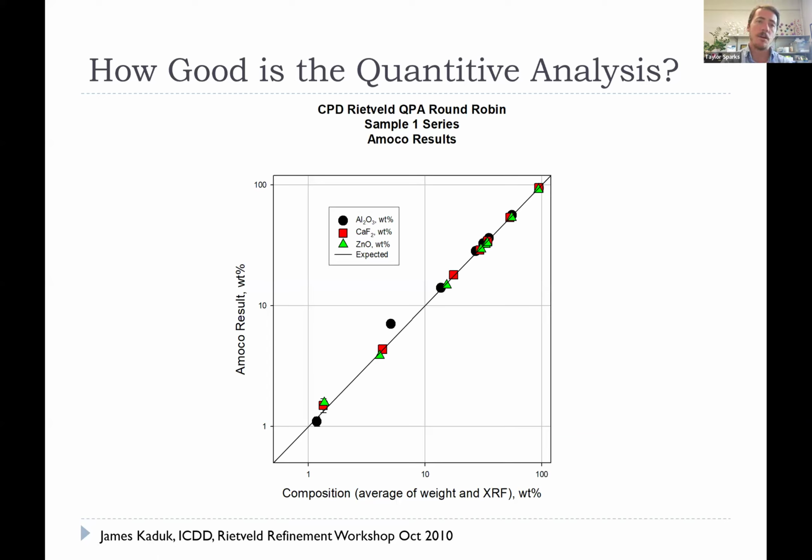If you're using lab x-rays, like if you're working in industry or at a national lab, and you're doing just a regular benchtop or a standard X-ray diffraction system, you can expect to get weight fractions accurate down to a few weight percent, like maybe 5 weight percent. If you're reporting less than that, I would start to become skeptical.